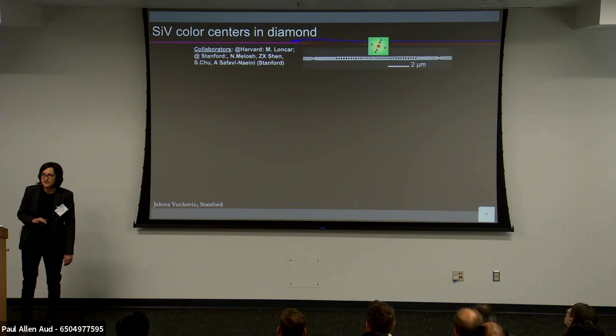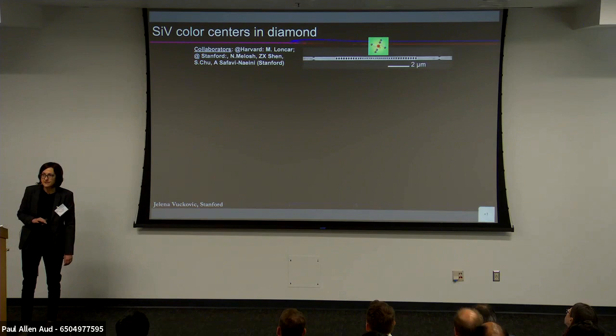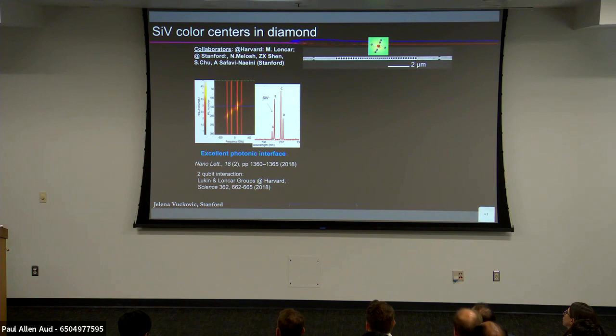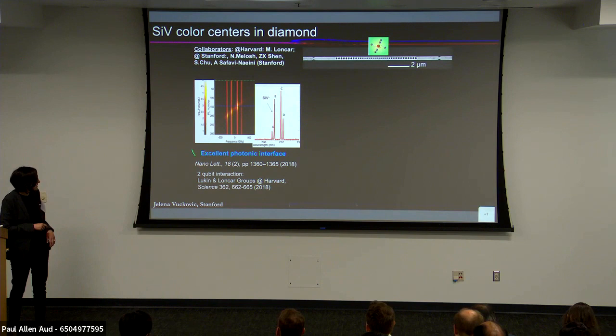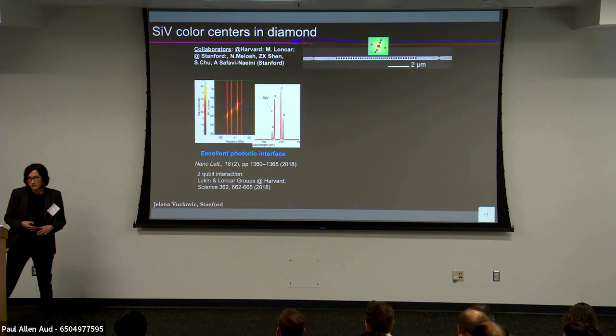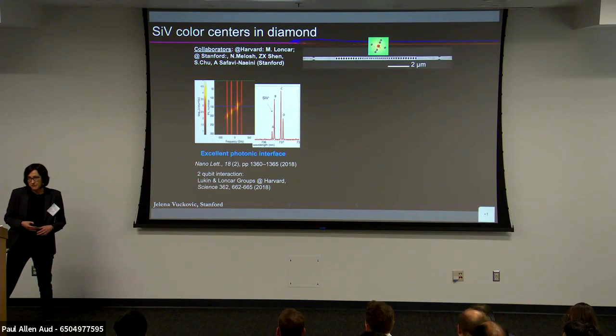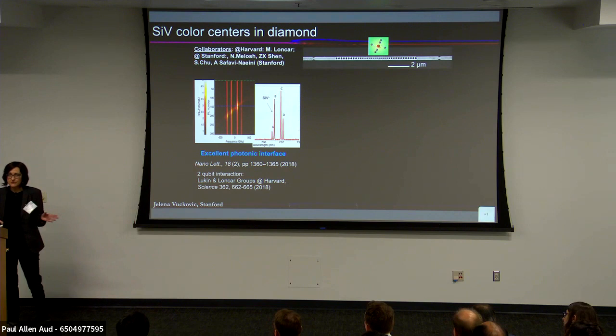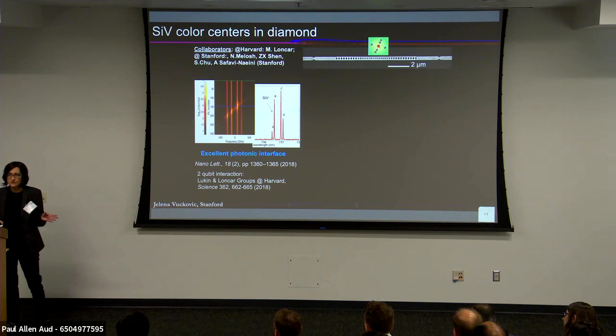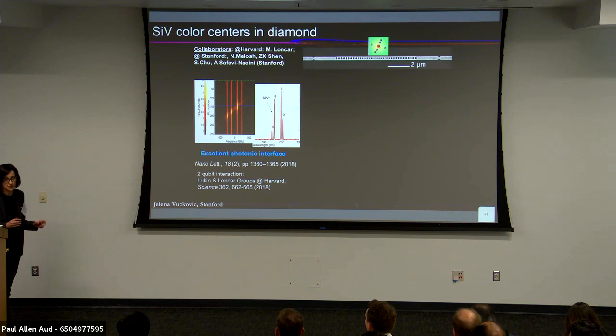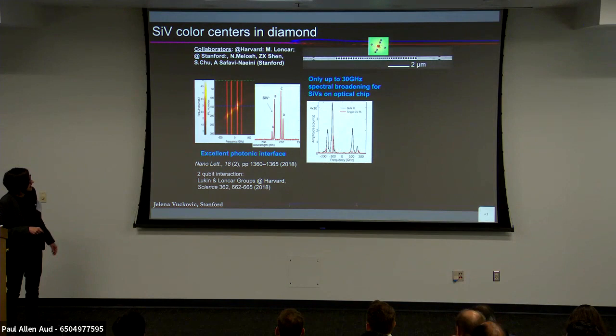Where do we stand with silicon vacancy in diamond? Here is a one-slide summary of the state of our research and the field. We have excellent photonic interfaces and long-lived qubits. Electron spin coherence times are in the millisecond regime, which is comparable to superconducting qubits, but these systems are also faster. Dividing coherence time by the speed of operation, you can build even larger depths of quantum circuits. This has been demonstrated by our group and also at Harvard and other places.